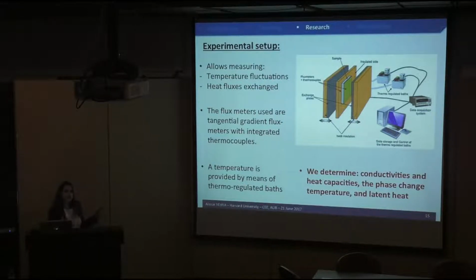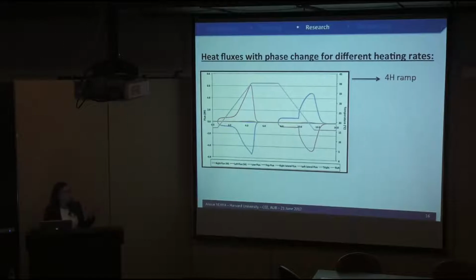However, these are not the only properties that we need for a phase change material. They are very important, but we have a lot of other complexities. So this is what we obtained from the experimental setup. We obtained the heat flux. As we can see here, we have a ramp of increasing temperature from 15.8 degrees Celsius to 40 degrees